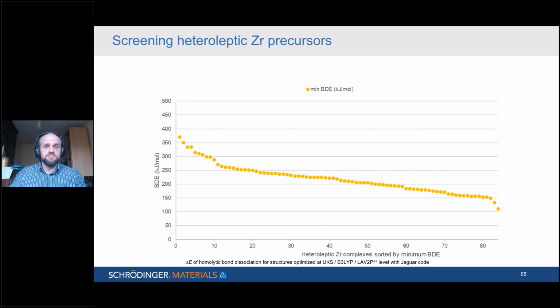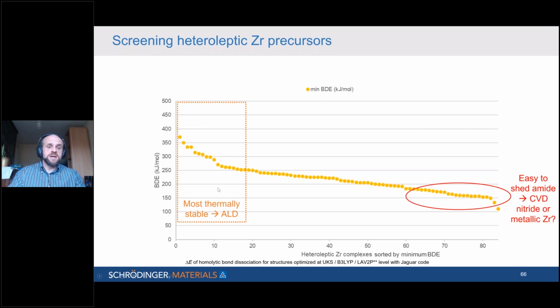So that's what I'm showing here, the minimum bond dissociation energy for the given molecule. And based on this now, we can start to make a selection. For example, for atomic layer deposition, you really want thermally stable molecules. You don't want them decomposing. They should reach the surface intact and only then lose their ligands, as I showed you in the previous surface calculations. So we would choose some of these molecules on the left-hand side with very high bond dissociation energies.